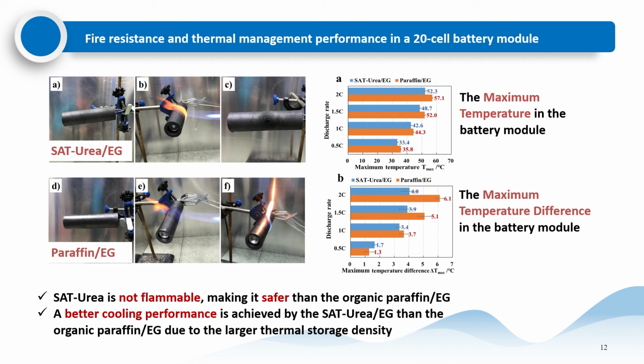And we also test the fire resistance of the salt hydrate and compare it with the organic paraffin EG. From the figure on the left, we can see that if we move the fire source away from the salt hydrate, the SAT urea, the fire stops. However, in the case of the organic paraffin, even when we move the fire source away, the paraffin EG continues burning. So we can conclude that the inorganic PCM is safer.